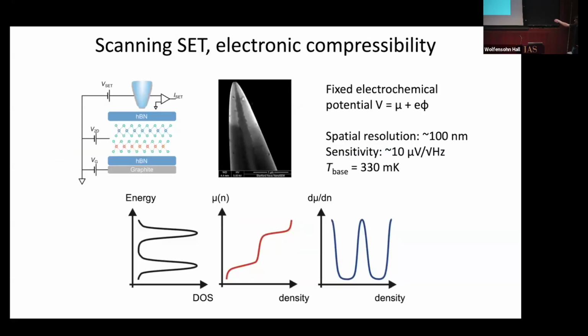Our electrostatic environment is provided by the sample. We hook a lead up to it that fixes its electrochemical potential. And so as we tune the carrier density with a backgate, that changes the chemical potential of the system, and there's a corresponding change in the electrostatic potential, which is what we sense with our device. And again, anytime you have a peak in the density of states, the chemical potential doesn't change very rapidly. Anytime you have an energy gap or a low density of states, you get a step in chemical potential, or a peak in dμ/dn, which is what we measure. So anytime you see a large signal in our measurements, that corresponds to a case where there's an energy gap in the system.